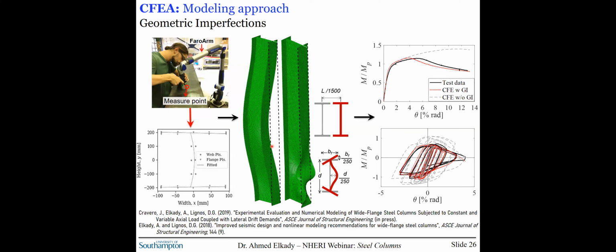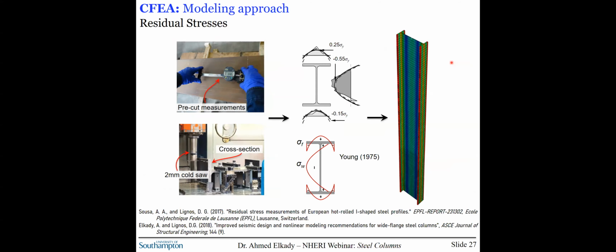Now, it's crucial that the proper amount of geometric imperfection be added to the finite element model to capture the right response. As I show here in these comparisons, if you totally ignore geometric imperfections in your model, you can be orders of magnitude off when it comes to your prediction. But also when you include geometric imperfection, you have to include the right amount, not too much, not too little, in order to trigger the local and global instabilities at the right time. In the same way, using the sectioning method, we measured the residual stress profiles resulting from the manufacturing process in different cross-section sizes. And from this, we were able to find the most appropriate residual stress distribution that we should consider in our model.